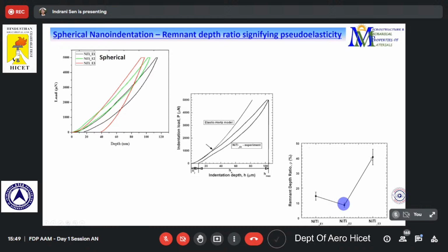Again, we did spherical nano indentation to figure out the depth recoverability, and we found that the one prepared with the highest energy density actually shows the least recoverability. This value signifies the extent of permanent deformation. A remnant means something that is permanent, that does not recover even if we are unloading. So that remnant depth ratio is highest for this E3. But interestingly, what we found is that this E2 alloy, prepared with an optimized value of laser energy density, shows a very good value of recoverability.